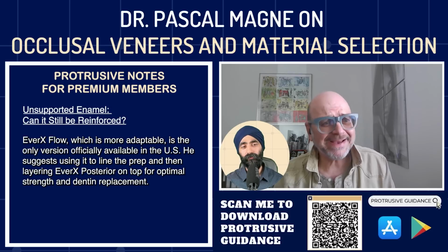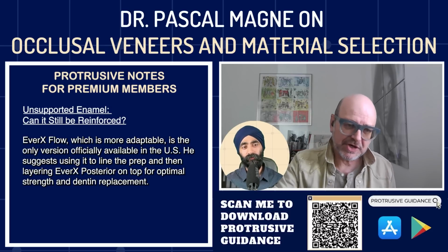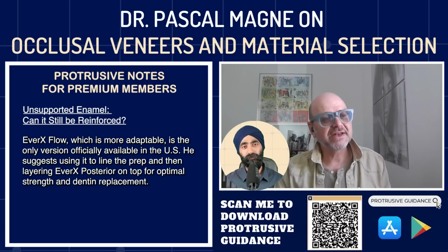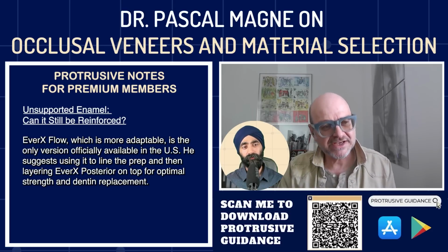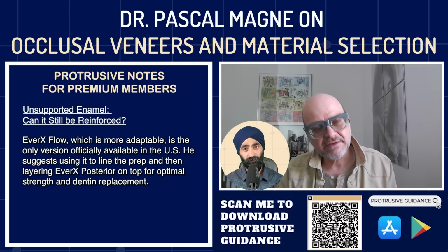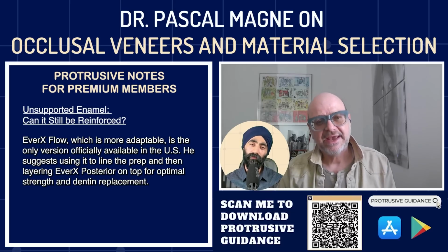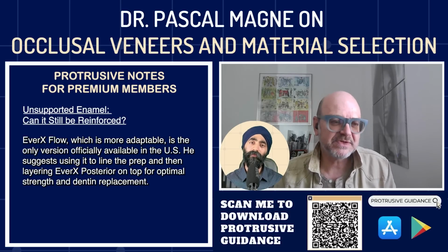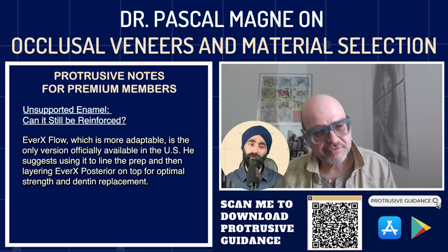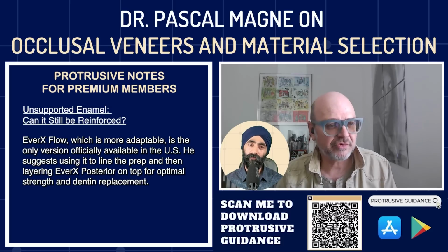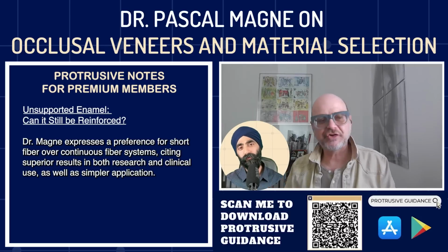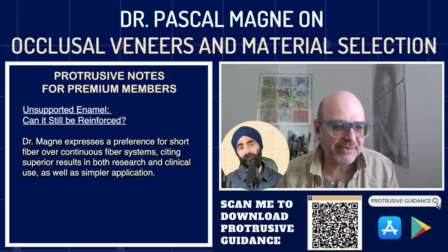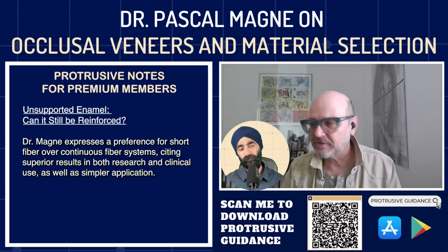So if you combine EverX Flow to fill the bottom of your preparation, and you can leave it unpolymerized, and then use EverX Posterior preheated, it is easier to place, and you have a wonderful dentin replacement with a material, the fibers of which will act really as a reinforcement. And to me, I would favor that over continuous fiber. I've never been a big fan of continuous fiber.